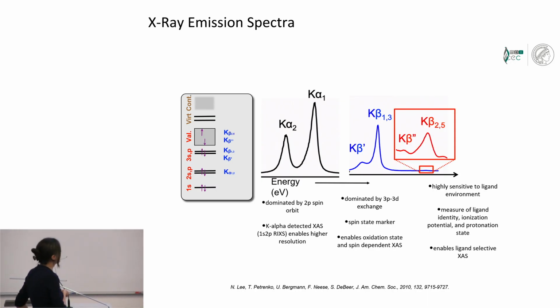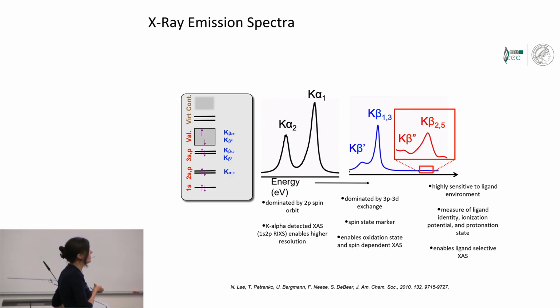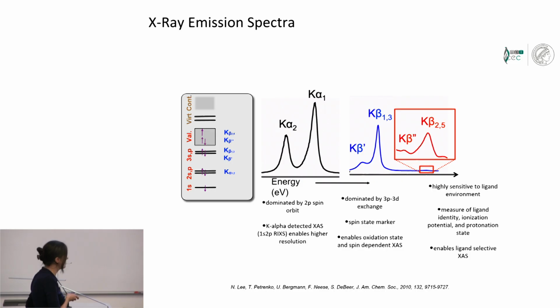And then finally, at very, very low intensity, I've boxed it in here so you can actually see it, are these valence to core transitions. And this corresponds to the very low probability that an electron in a ligand-based valence orbital refills the core hole on the metal. And this is highly sensitive to ligand environment, and it's a good measure of ligand identity, as well as ionization potential and protonation states. And this can also enable some exotic experiments that I will briefly touch on.